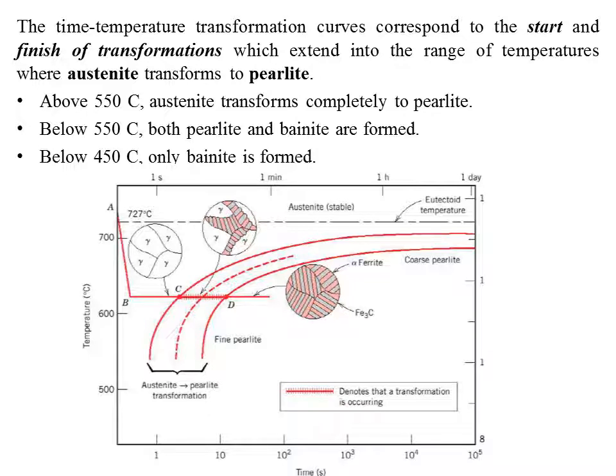Hence, the TTT curve corresponds to the start and finish of transformation, which extends into the range of temperatures where austenite transforms into pearlite. So here it starts and then it transforms to pearlite. You can see at a temperature of 727, the eutectoid temperature, the transformation starts, and when the austenite is converted, the material is transformed into pearlite. So above 550 degrees centigrade, the austenite transforms completely into pearlite. Then below 550, both pearlite and bainite are formed. But below 450, you will have only bainite.